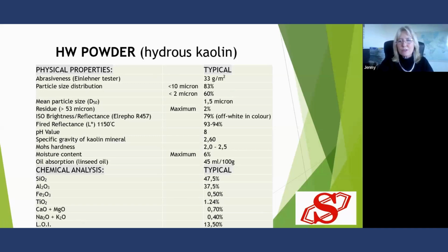There's two ways to purify kaolin when you have a kaolin deposit. You can either water wash it, which is a very effective way of removing the impurities. The main impurity that occurs with kaolin is silica. That's what we had when we had our kaolin deposit, and mica was the second largest impurity. The water washing process separates on particle size using hydrocyclones, and it takes out the biggest particles. Luckily for us, the biggest particles were silica. And then the next biggest ones were mica. So that's how we got nearly pure kaolin.